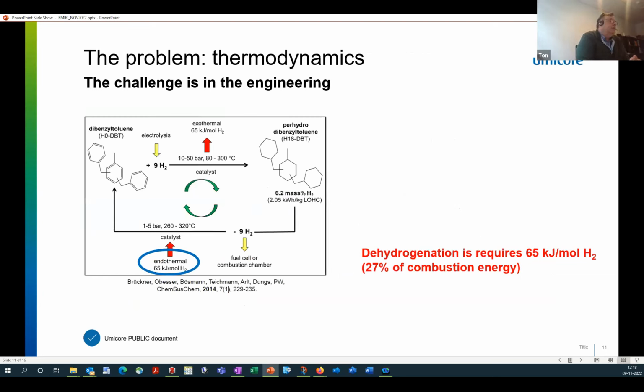So far so good. But there is also a problem, and that is the thermodynamics. It has already been mentioned before. To store the hydrogen in the molecule, we have an energy release of about 65 kilojoule per mole. And to release it, so in the application, we have to provide this 65 kilojoule per mole. And 65 kilojoule per mole is 27% of the combustion energy of hydrogen. So it essentially means that we actually lose about 30% of the energy content in the hydrogen that we want to use, just to keep that reaction going.